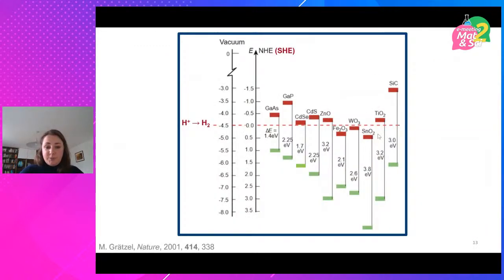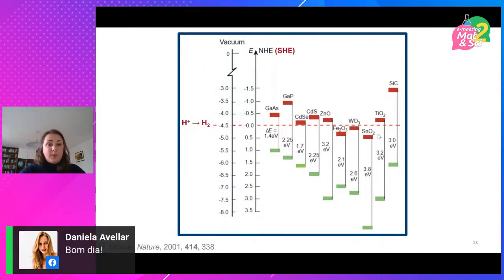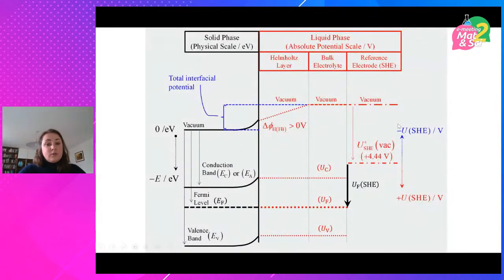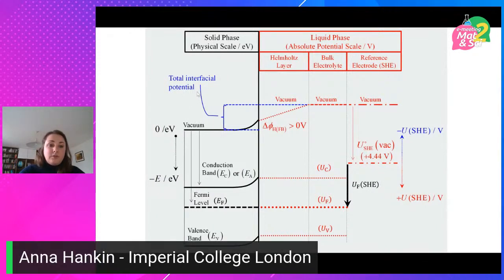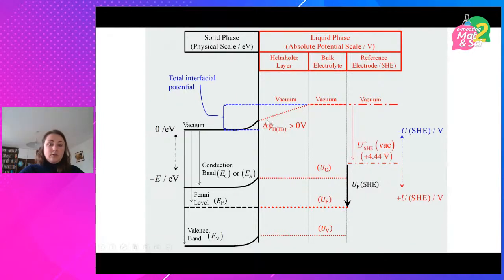And that something is also missing from representations like this, where bands of the semiconductor are plotted both against vacuum and versus the standard hydrogen electrode. There's always an assumed offset, but actually that offset is not the same for different semiconductors, and it's not constant at different potentials. So it actually changes. Why does it change? Because at the interface, you have the band bending of the semiconductor, which we all know happens, but you also have a potential drop across the Helmholtz layer, so that your actual total interfacial potential is a sum of the band bending in the semiconductor and the potential drop across this Helmholtz layer.